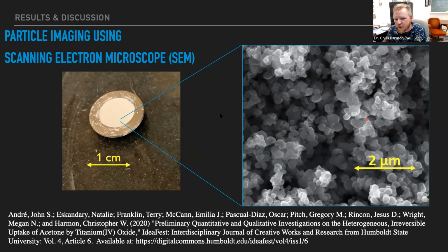Okay, and so here you can see what those particles look like, and they are fluffy. There's space between the particles, and that's what we want. And you can also see these particles are on the small side. So we noted that representative mineral dust is about 2 micron. And our particles are a bit smaller than that, but still within a reasonable size for atmospheric relevance.